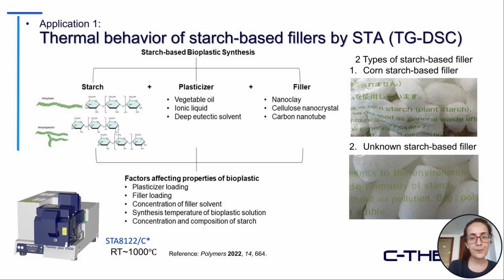The second example I want to talk about is the thermal behavior of starch-based fillers by STA, TG-DSC. Starch usually consists of two phases, amylose and amylopectin. Amylose is the amorphous part and amylopectin is the crystalline part. In this example, starch is blended with plasticizers and some fillers, namely nanoclay, cellulose nanocrystal, and carbon nanotube. And we use two types of starch-based filler. One is a corn starch-based filler, and the second one is an unknown starch-based filler.